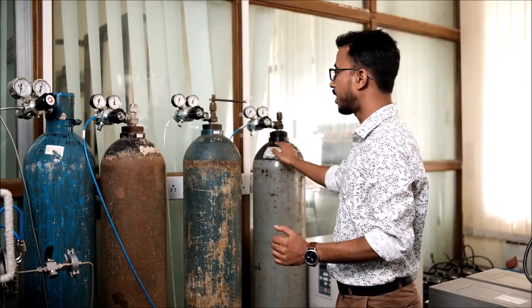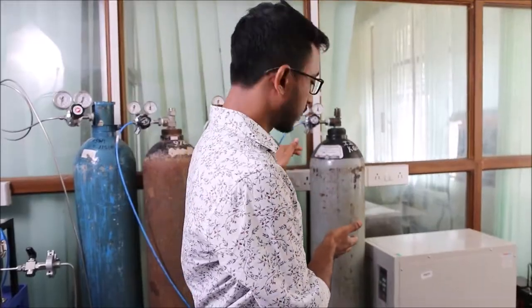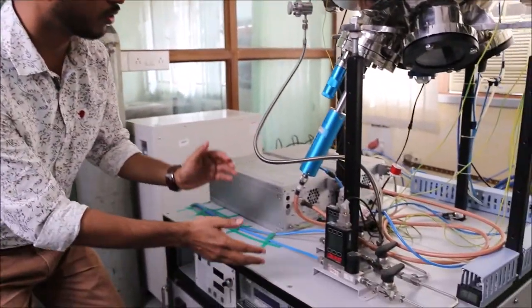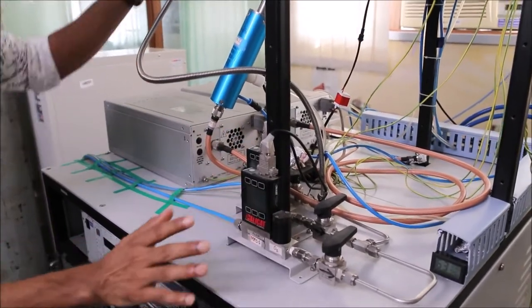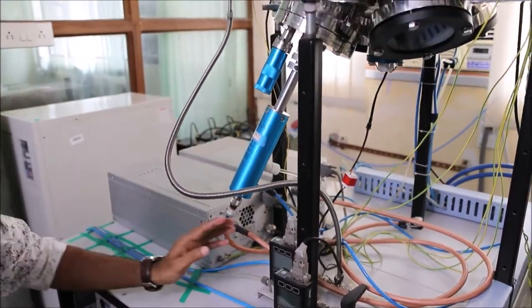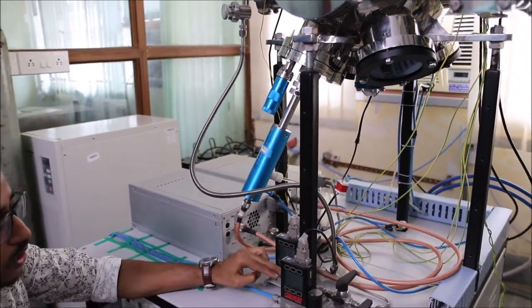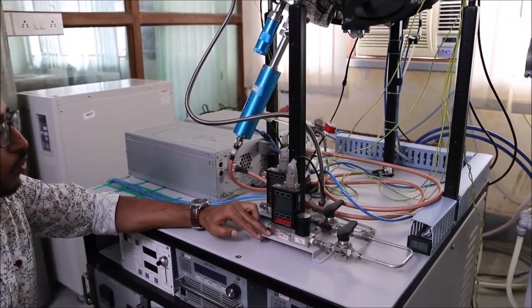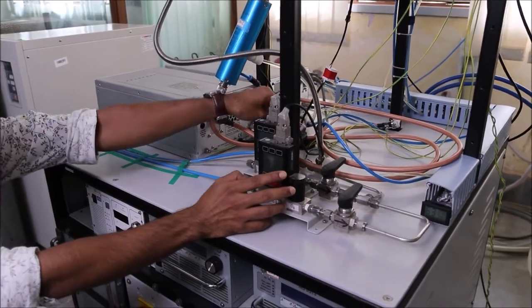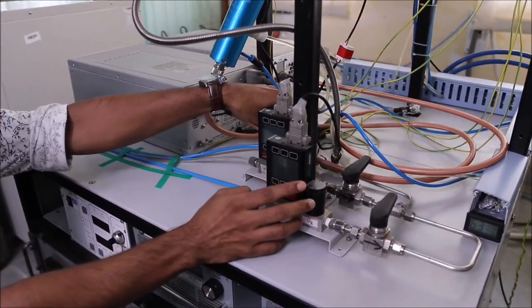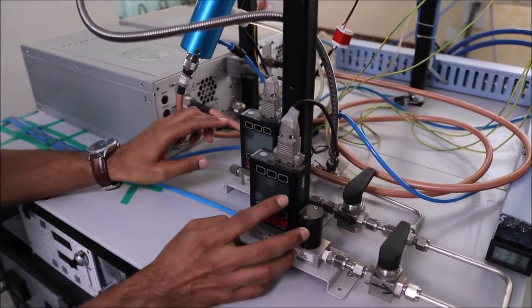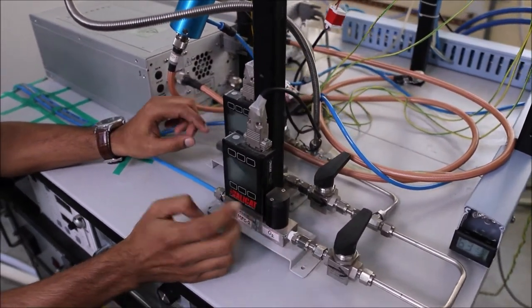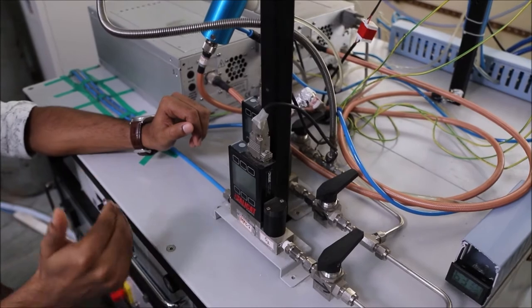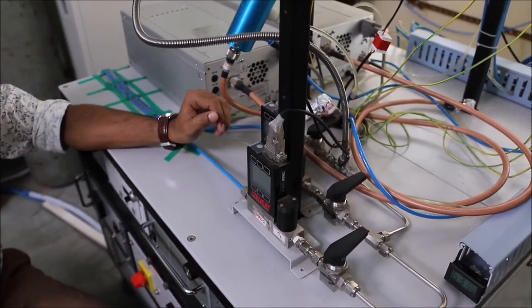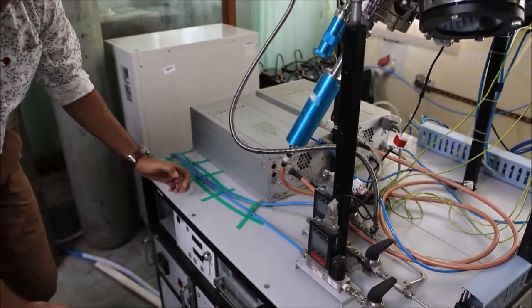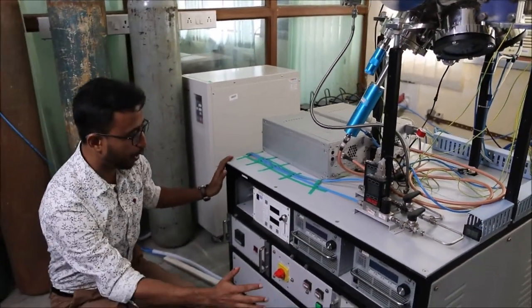So these gases are passed through the regulator, and then the gases come through the pipe, and through the mass flow controller, it enters into the chamber. And we have two mass flow controllers. One is for the argon and another is for the oxygen. We don't have any mass flow controller for the nitrogen, because for the venting purpose, we don't need that much control. And through these buttons, we control the outflow of the gases so that we can maintain a particular ratio for our deposition system.